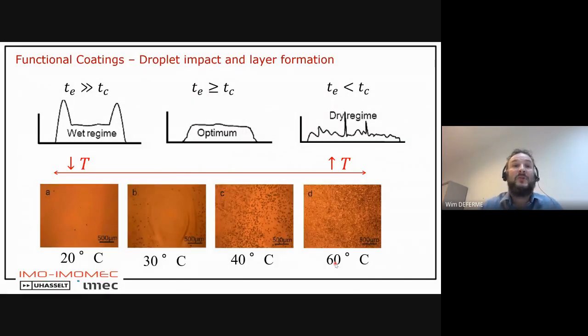And there is a lot of research done already on this. And for ultrasonic spray coating also, there is some research there. Then we talk about the amount of wet droplets that arrive at the substrate. You have the wet regime, the dry regime, and the optimum. In principle, the distance between the nozzle and the substrate in ultrasonic spray coating is a few centimeters, 5 to 7 centimeters. That means that if you have a droplet of 20 micrometers, during the flight, and depending on the speed, depending on the surrounding temperature and so on, partly your solvent will evaporate.